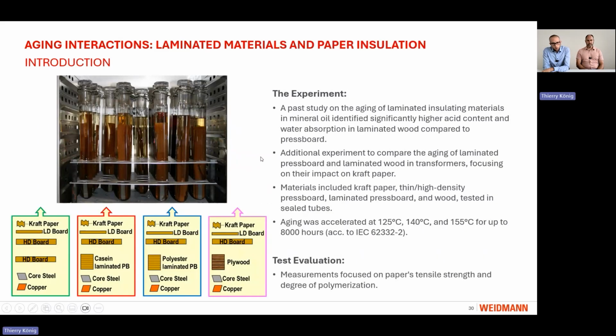The next experiment I want to present is about laminated materials. A past study revealed that aging of laminated wood generates a higher acid content and higher water content. Therefore, an additional experiment was developed to analyze the impact when we age multiple materials in the same vessel, and we focused on what happens to the paper in that test vessel.